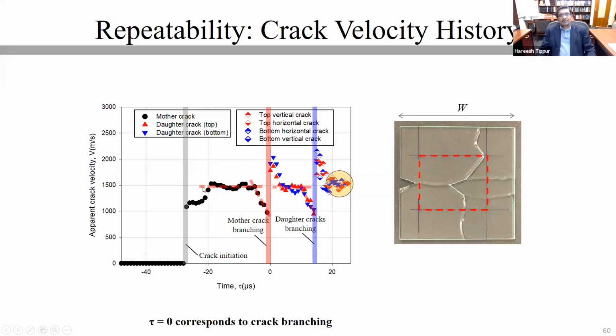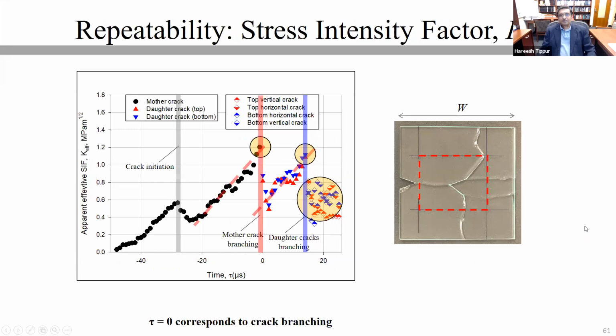So even in this case, when you plotted the crack velocity histories, we see that the mother crack was still propagating around 1500 meters per second, slowed down, and jumped to a very high value of 1800 to 2000 meters per second, settled down to again 1500 meters per second, slowed down again, branched, and then produced four granddaughter cracks, four cascading crack branch formations. And that again settled down to another 1500 meters per second without further branching event. So no branching took place beyond the second set of branches.